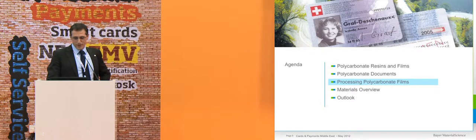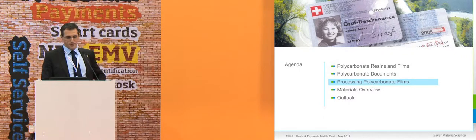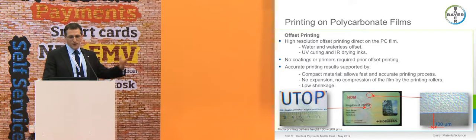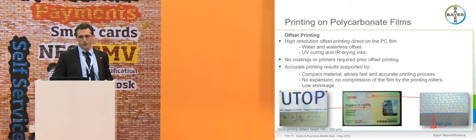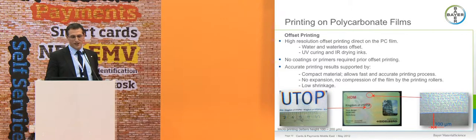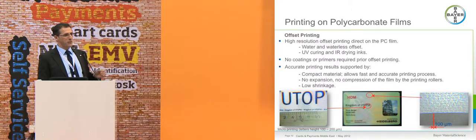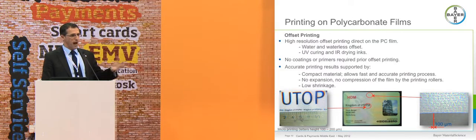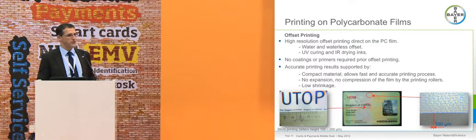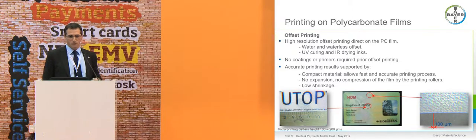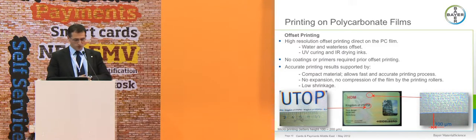So let us go to the key point here, processing of polycarbonate films for making these documents. First, the most important processing step for polycarbonate, which is the high security printing, which is typically done with offset. Printing on polycarbonate is possible with standard offset printing technique. That means water or waterless offset printing technology with UV curing inks or infrared curing inks. There are no coatings or primers required onto the polycarbonate film in order to make it printable. You can print on the surface as you get it from the supplier.